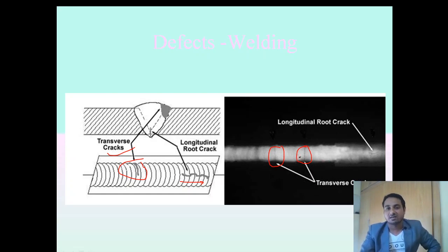A very fine line, but a very dark line, so that will be a crack, a transverse crack. Now the longitudinal crack. Here you can see this is my longitudinal crack. You need to be very careful while reviewing the film not to miss these cracks, because in any acceptance criteria, any code, it is not accepted. We need to cut and rebuild it.